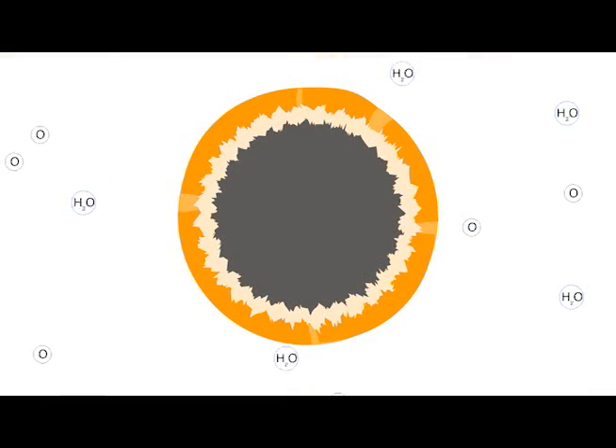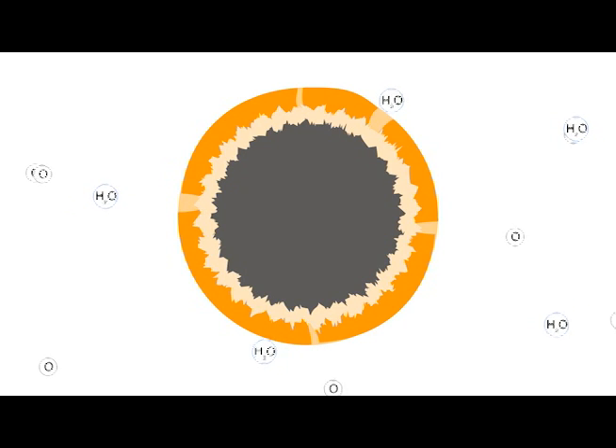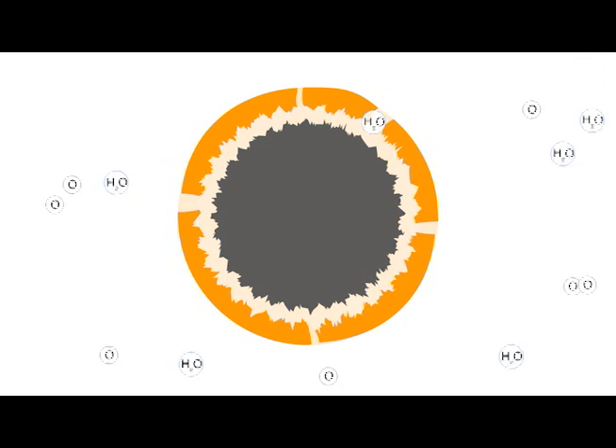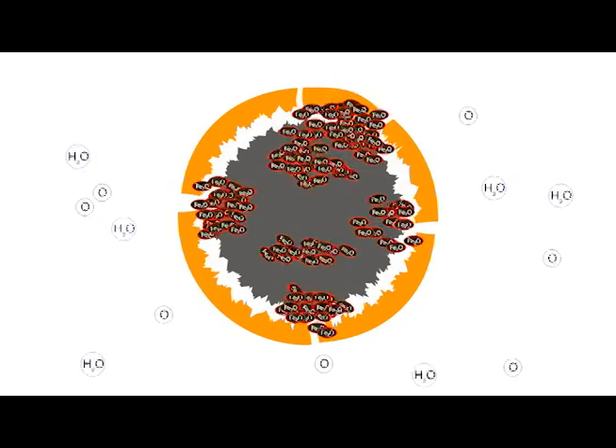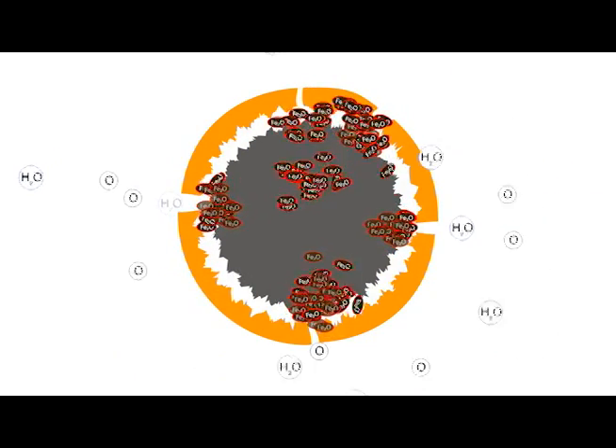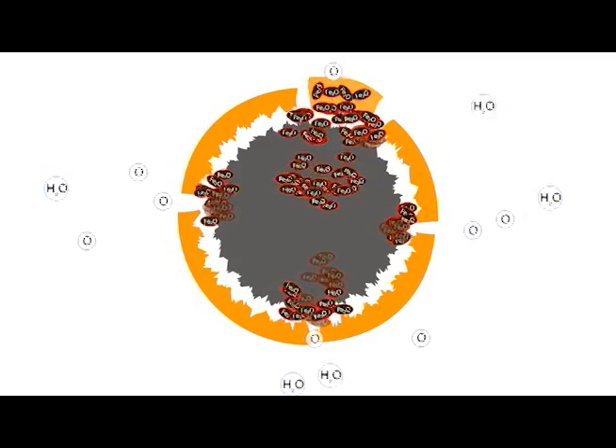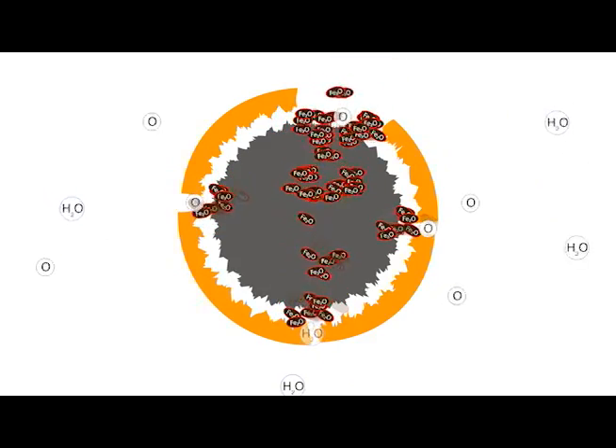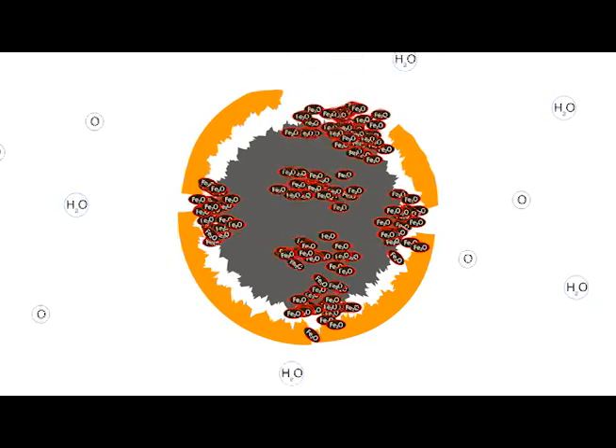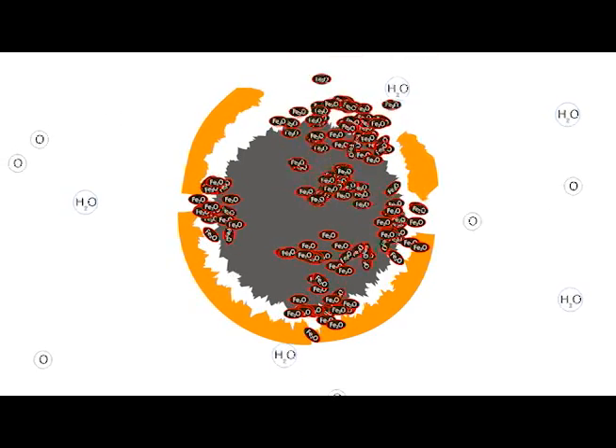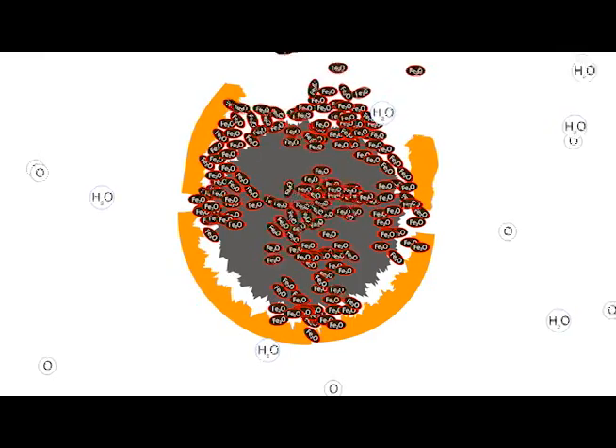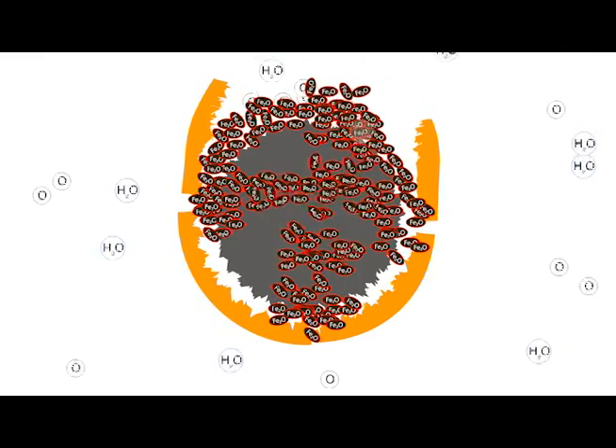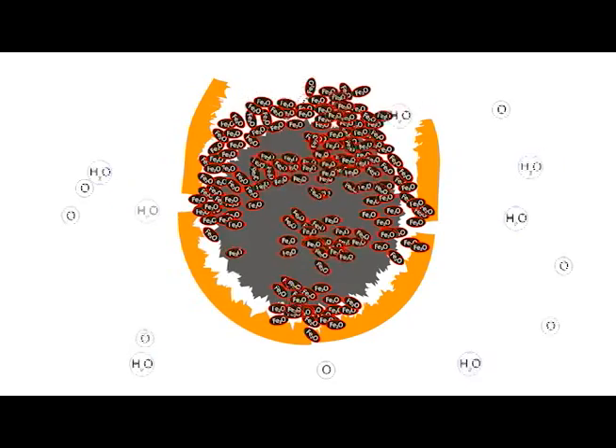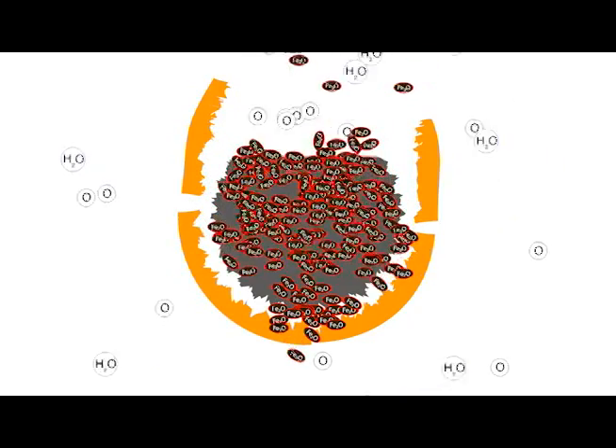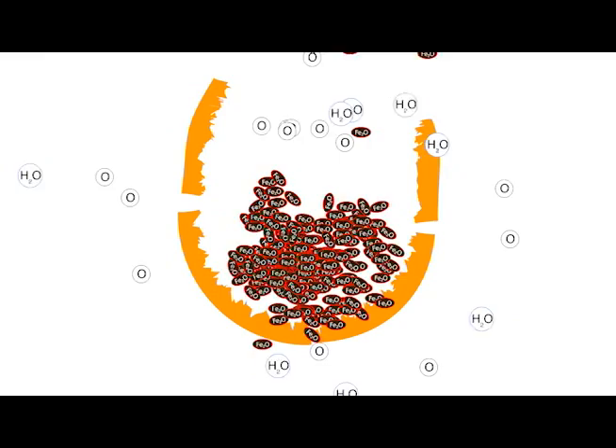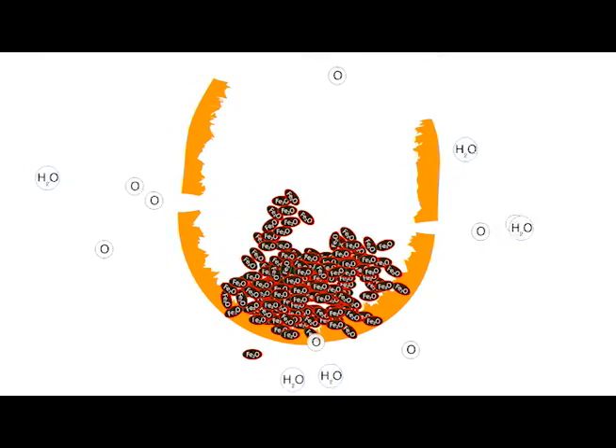Intergranular and galvanic corrosion are precipitated by the steel's exposure to the atmosphere, accelerating the mounding of pressure-inducing oxides, sulfides, and carbonates. This serves to further crack and peel back the copper cladding. This process will continue until all of the iron molecules are oxidized and removed from the core, leaving a cracked copper tube in its place. At this point, the ground grid has been compromised and is no longer in full control of abnormal current. This leads to a hazardous and destructive condition for the substation.